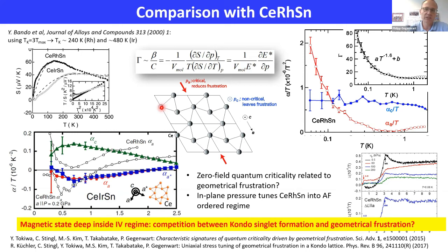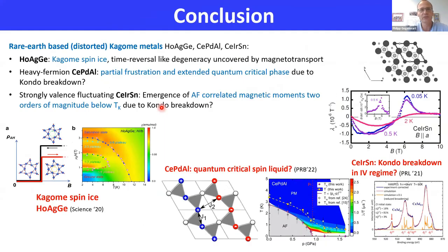So the remarkable observation and the task for theory, of course, now is also to understand how we could have such emergence of magnetic moments with antiferromagnetic couplings deep in the intermediate valence regime, where we wouldn't have expected them. And so our preliminary expectation may be that the geometrical frustration competes with the Kondo singlet formation, and as a result of this competition, some magnetic degrees of freedom are emerging at low energies. All right, so now I should come to the summary.